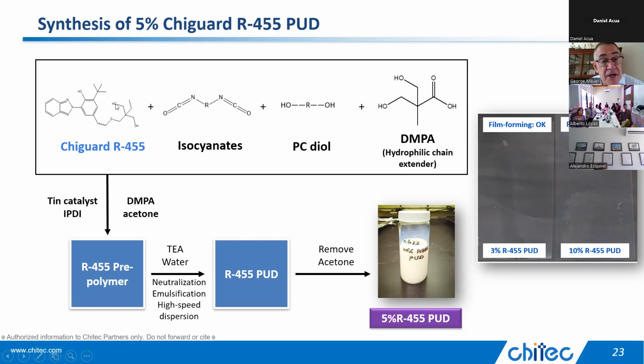The OHs here react with the isocyanate and gives you a urethane. Now, typically, you have other diols that you would use. They could be small, like neopentylglycol, or they could even be a hydroxyl prepolymer. For instance, a short chain polyester could be used. So there's a lot of different things that could be used as your supplementary diol. And then to make it water dispersible, one of the most common ways to do that is with dimethylol propionic acid. Basically, these hydroxyls will react with your isocyanate to form some urethane linkages. And then this acid group is what helps you emulsify it into your waterborne coating. It needs to be neutralized with an amine, dimethylethanolamine or diisopropanolamine or triethylamine.